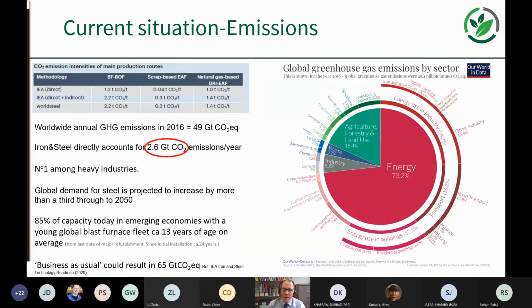So where are we with the current situation with regard to CO2 emissions? On the top left-hand side, I've got a table there from the International Energy Agency Iron and Steel Technology Roadmap. They produced a roadmap at the end of last year, actually. That emphasizes where we're at in terms of the specific intensity of CO2 per ton of hot metal. And there's some variation in the amount of CO2 that's produced per ton.